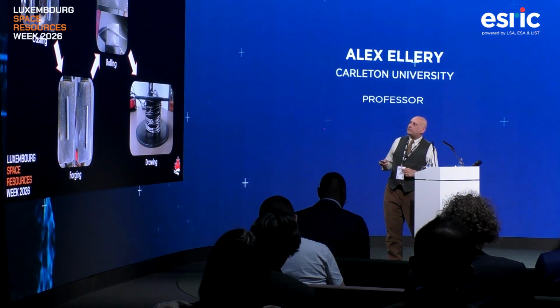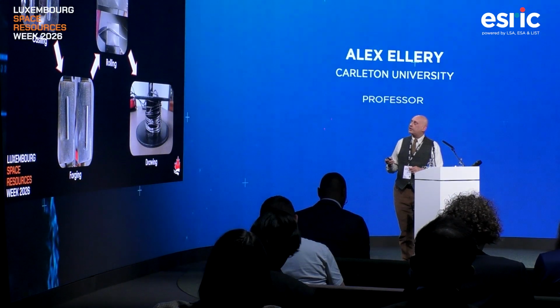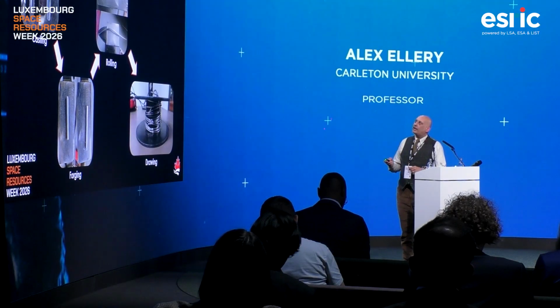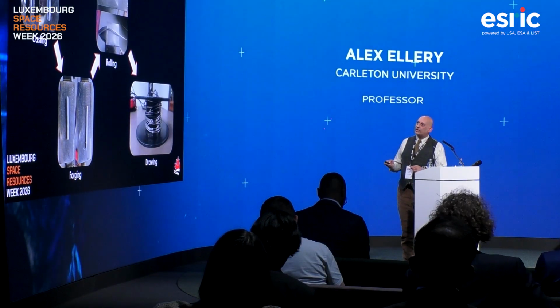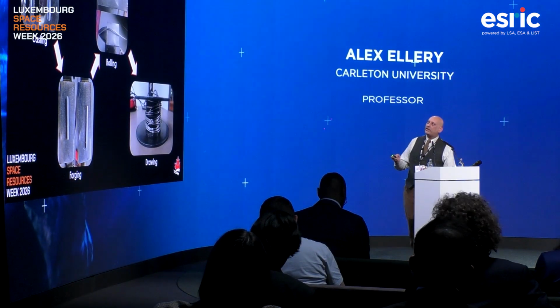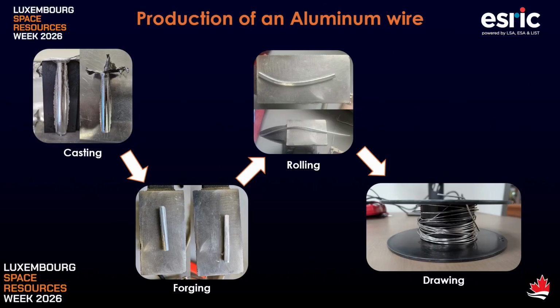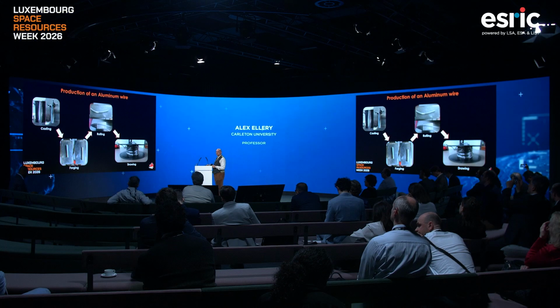So the next stage of the process was to try and use it as a construction material. We cast the molten aluminium in these casts here. We then processed it and cleaned it up a little bit, and then we rolled it very laboriously to thin it out a little bit, and finally drew it into wire, which you see spooled here.